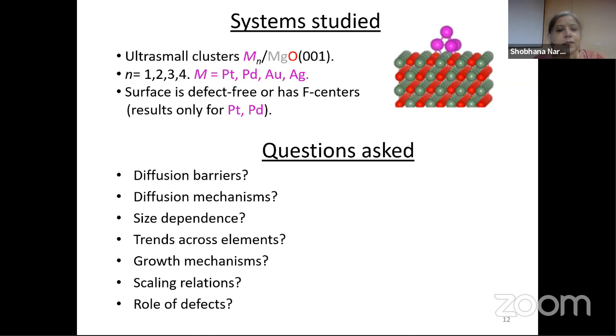thing we want to know is, so we are interested in studying these ultra small clusters of metal nanoparticles on an MgO substrate. And the elements we're studying are platinum, palladium, gold, and silver. And we're looking at whether the surface might be defect-free or it might have what are called F centers, which are oxygen-based species. And because we're interested in studying this process of sintering, we're looking at diffusion barriers, mechanisms, size dependence, trends across elements, growth mechanisms, scaling relations, the role of defects, etc.